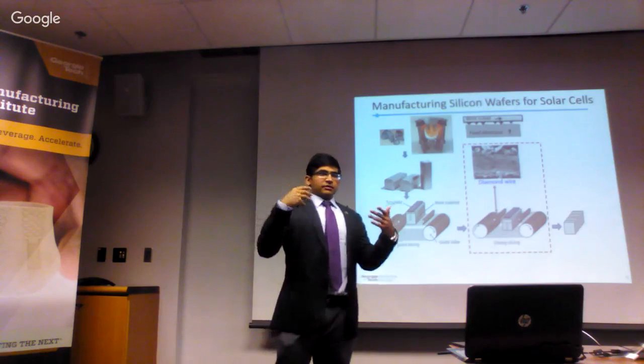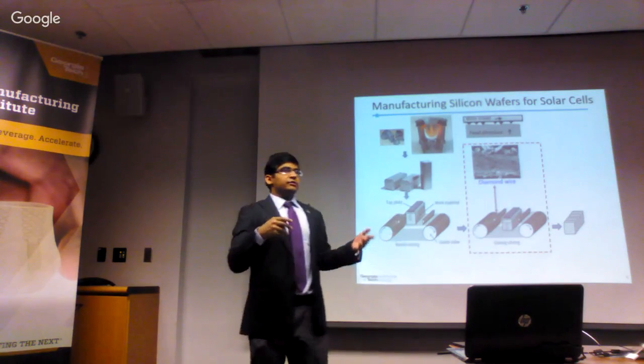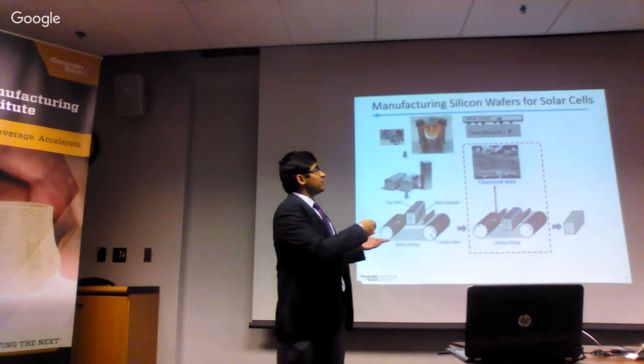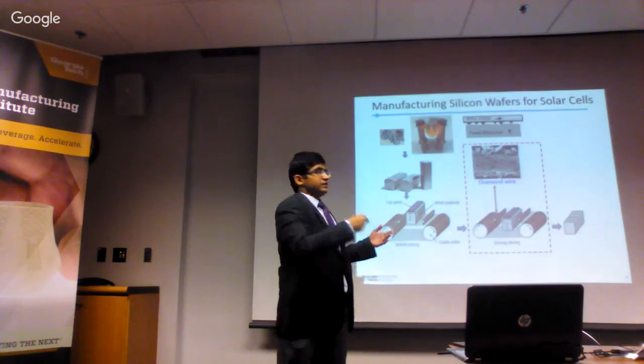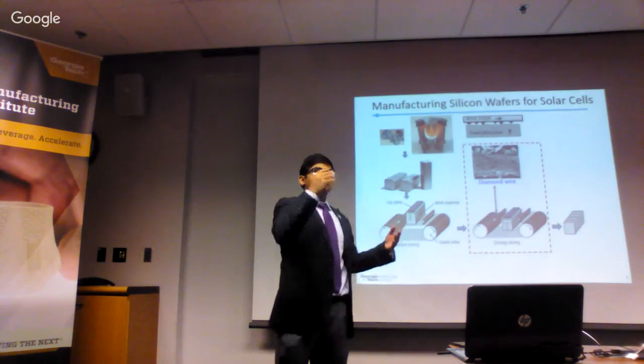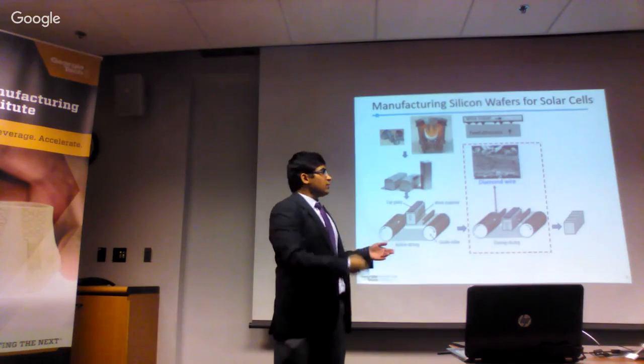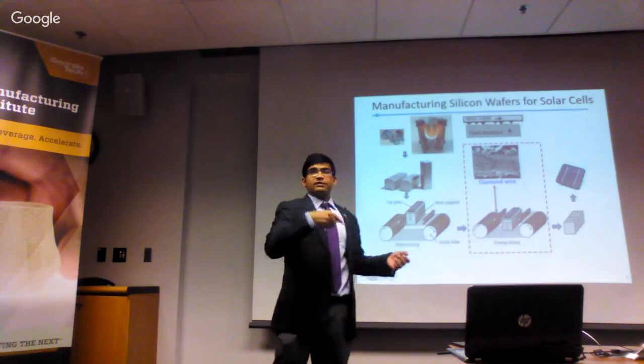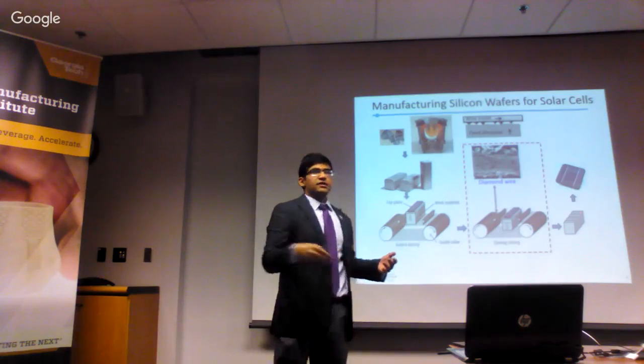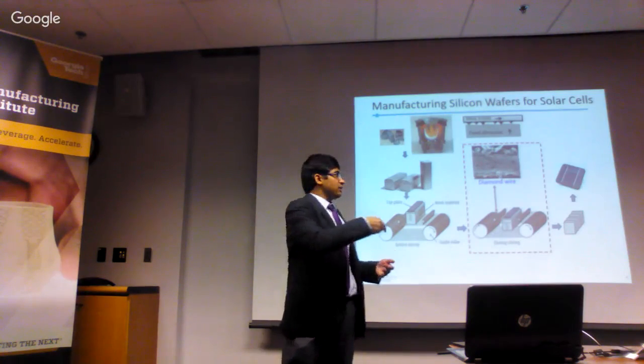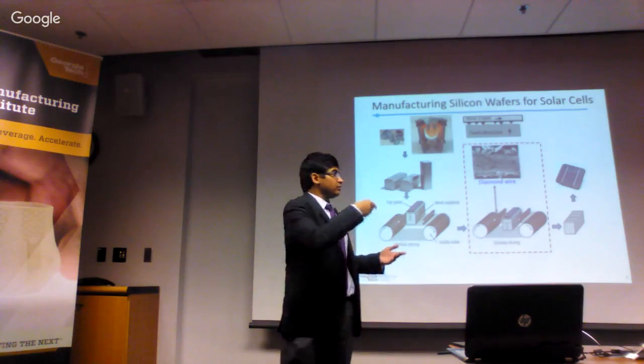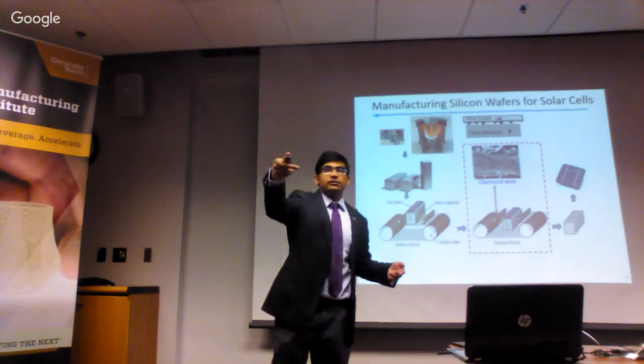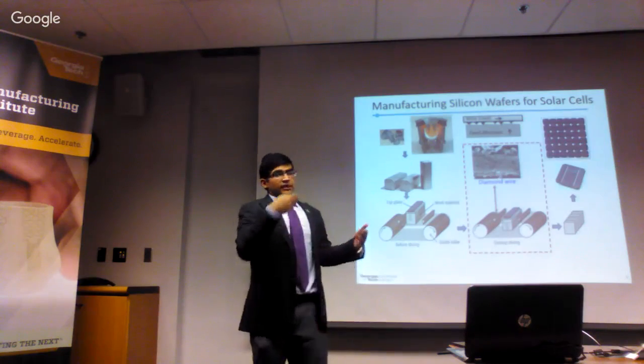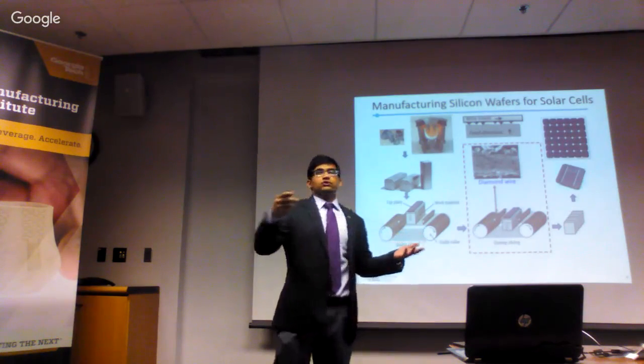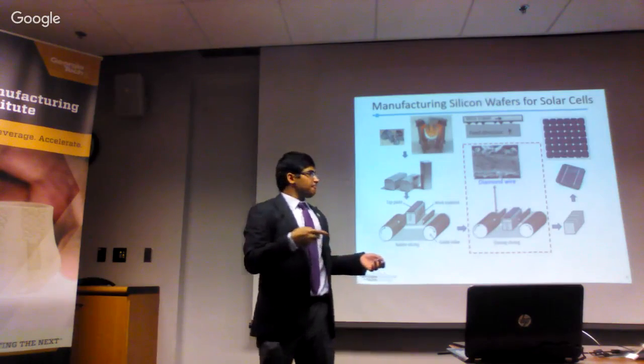This could be simulated in our lab scale experiments with the scribing or scratching process, because that's how the abrasives on the wire, as they are traveling through the wire, are removing silicon from the ingot and slicing them into thin wafers. To complete the story of solar cells, the wafers are further processed into solar cells through etching, doping, and giving an anti-reflective silicon nitride coating, which makes it look blue, as the solar cell which is passed around with you. And then the solar cells are put into modules, which go on our rooftops to give us energy.